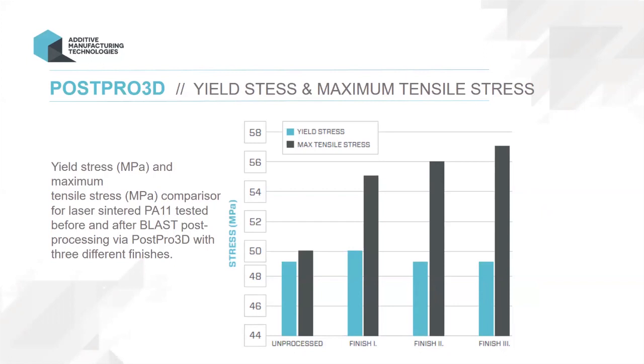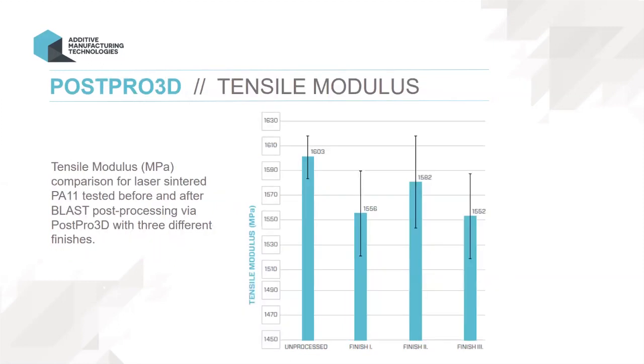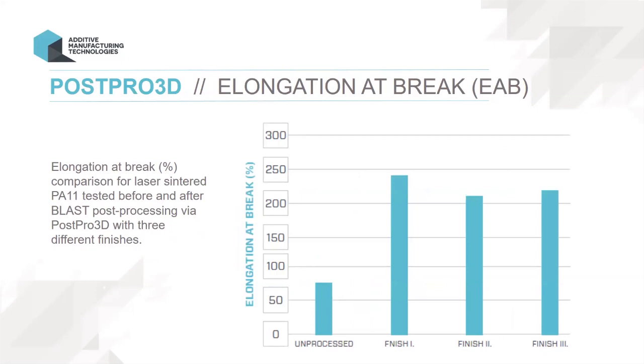And these charts give you an idea of the before and after tensile stress, the tensile properties and the uptick. Our technology will not change the tensile strength or the yield strength too much, but if we go to the next slide, David, you will see that we're also not changing the modulus, which is important because if we go to the next slide, we do have a significant gain in the elongation at break.